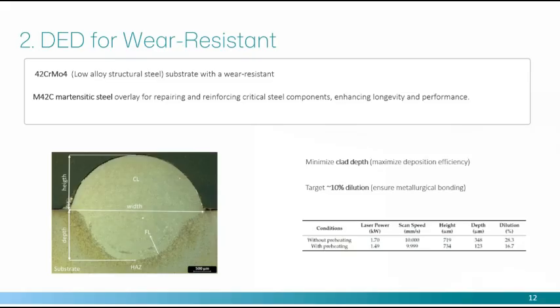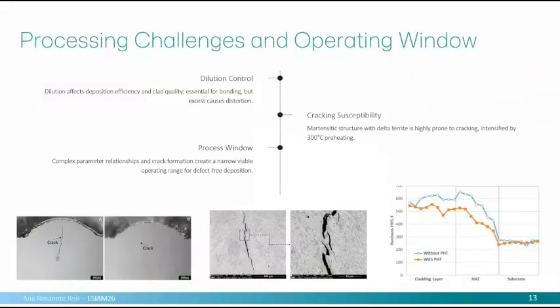What we want when we start experimental work is to minimize clad depth, of course, and also get some kind of dilution that guarantees us the bonding that we need. So, a lot of experiments until we get these parameters, and then we analyzed the results, and they were not good because everything cracks. The result is even worse with preheating.